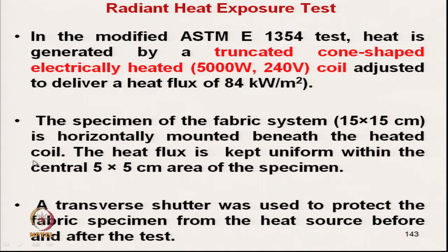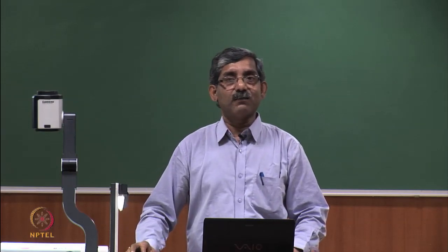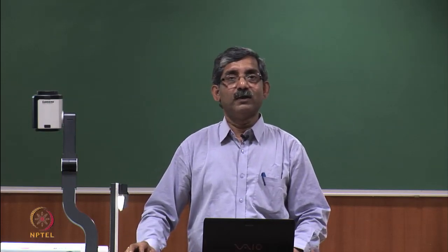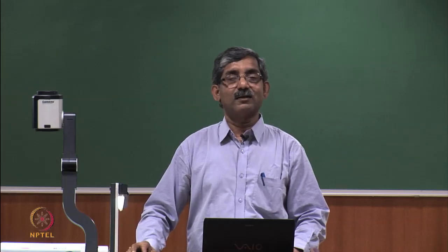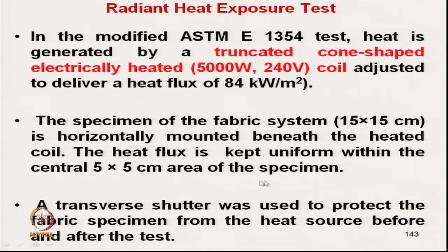It is placed just below the heated coil, and the heat flux is kept uniform within the center 5 centimeter by 5 centimeter area of the specimen.